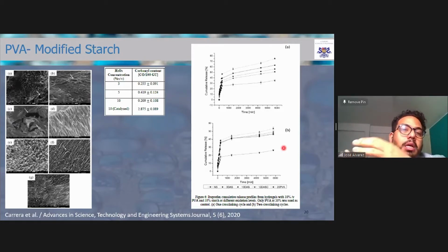swelling was lower. So you kind of have to compromise a little bit, and it depends on the application that you want to give. So if you want to look into tissue engineering, you probably would be okay with something that doesn't swell as much. But for drug delivery, you probably need something that swells a little bit more, because you can see here, for a large oxidation degree, you get only up to 20-something% of the ibuprofen released.